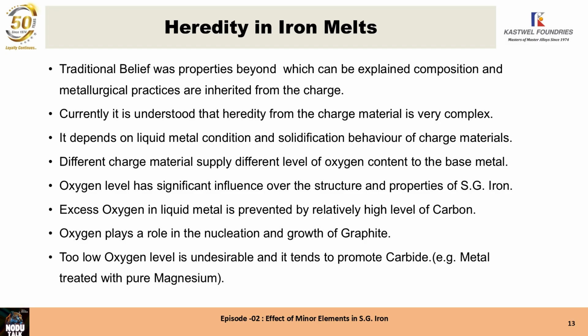This is one of the most important reasons why we have to keep the charged materials constant and of the same quality throughout our SG iron campaign. Different charged materials supply different levels of oxygen content to the base metal. Excess of oxygen in liquid metal is prevented in the case of SG iron because of the high carbon present in the liquid metal. Carbon doesn't allow oxygen to build up, so the high level is prevented.